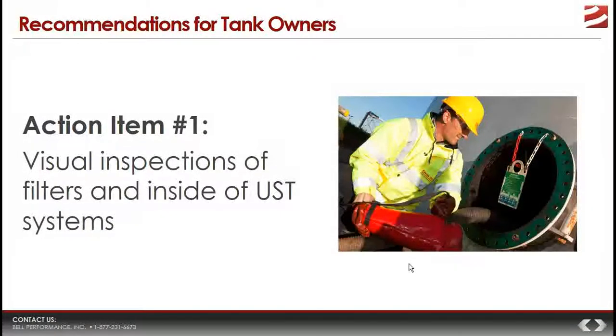And they need to do this on a regular basis, and importantly, even if they haven't seen any symptoms. And it doesn't matter if the tank's fiberglass or steel, they need to do this. That's action item number one. Again, the reason why, as we said before, it was established that you can have severe corrosion problems in that tank, and it can be going on even before any symptoms really show up. Again, remember, less than 25% of those tank owners thought they had a problem, but yet 80% of them did.